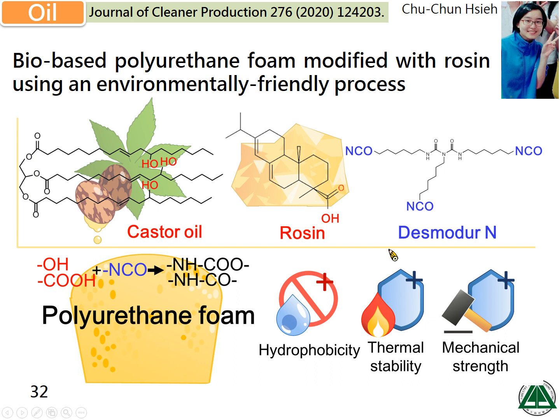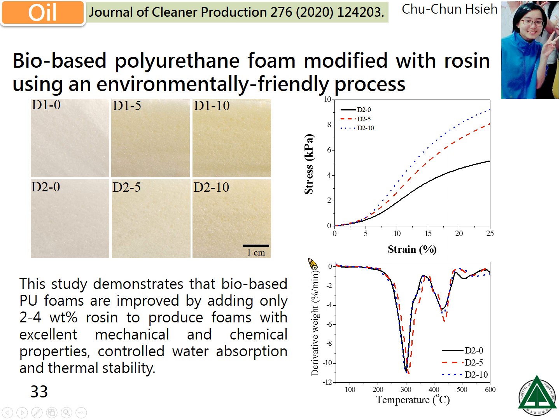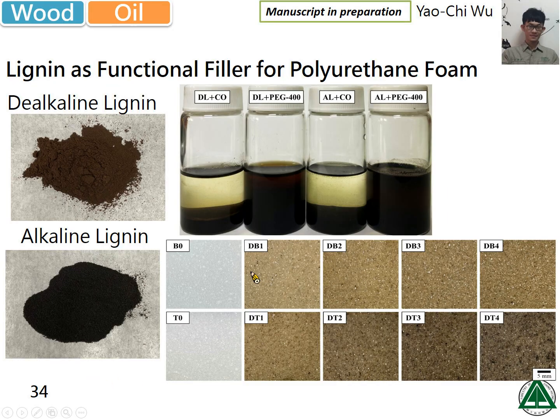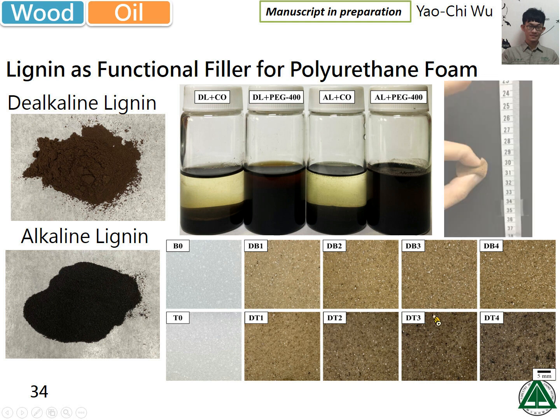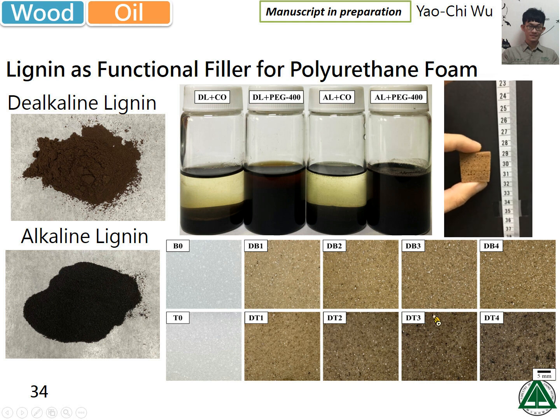We also use rosin to improve the property of castor oil-based polyurethane foam. I think from the structure you can imagine it is really hydrophobic. Moreover, maybe it can increase the thermal or mechanical properties. These results demonstrate the bio-based polyurethane foam is improved by adding only 2 to 4% rosin. We can produce the foam with excellent mechanical and chemical property, and we can control the water absorption and thermal stability. Lignin can also be used as functional filler to prepare polyurethane foam. Moreover, as lignin can increase the bio content, we can get homogeneous foam with flexible property. We can use it for some cushioning products.